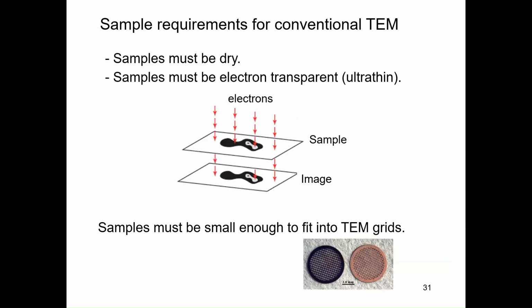So the sample requirements for conventional TEM, again, samples must be dry, and also must be electron transparent, ultra thin, because electron beam coming from the top and then have to transmit through the samples. And if the samples have electron dense area, the electron gets scattered. And here is the detector, so the electrons don't get to the detector, and then that area would be black. But if there's an electron transparent region, then we get some electrons collected by detector, and so that can be a principle of image formation in a TEM.